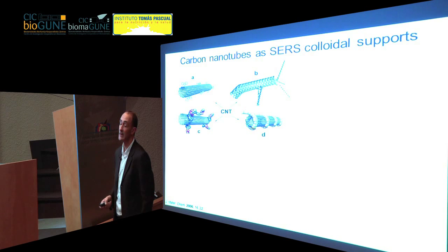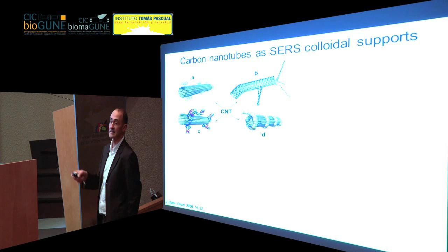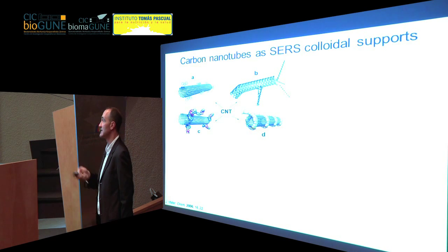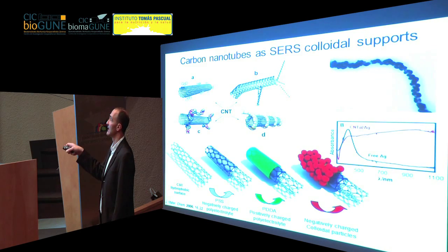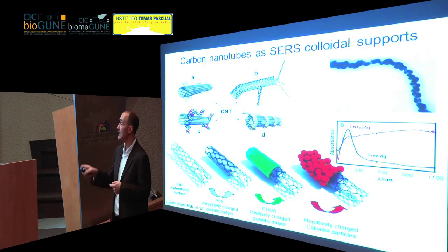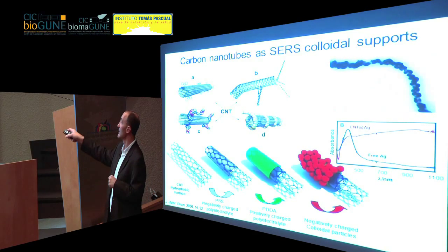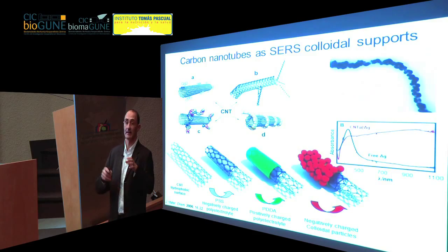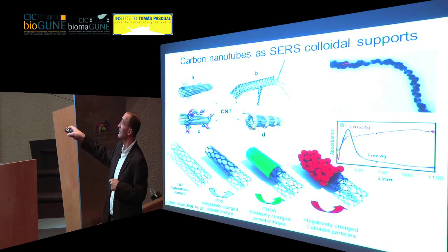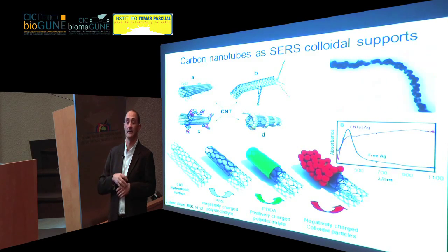So this is one example where we created these SERS substrates by using carbon nanotubes as templates. We know the chemistry of this type of materials quite well. We know that we can deposit polyelectrolytes on the surface of the carbon nanotubes, creating charges on the surface. And then we can adsorb particles directly because of electrostatic interaction. So we can get this type of materials that can be suspended in water, and then we can put them in contact with the biofluid that we want to analyze.